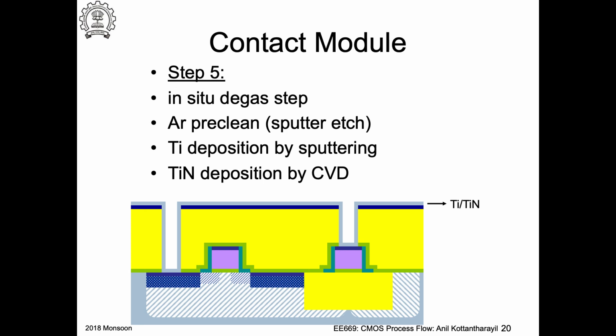So you do what is called an in situ degas step, essentially to get rid of this dielectric. So you actually do a sputter of the surface using argon, and then you deposit a stack of titanium by sputtering, okay, and then titanium nitride. Yeah. So you deposit titanium by sputtering and titanium nitride by CVD. So titanium is a metal, so it gives a good, low resistance to your silicide, and then you put titanium nitride.